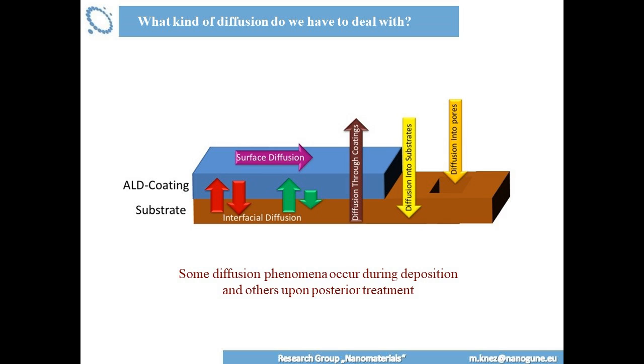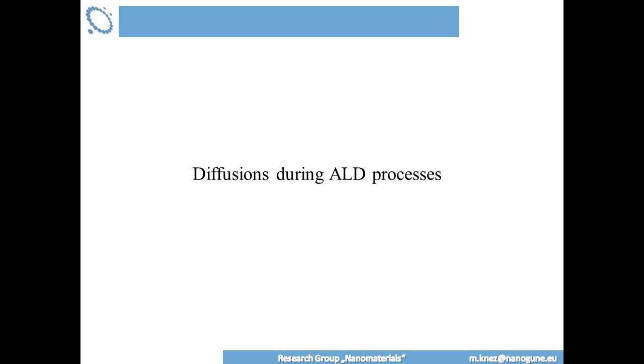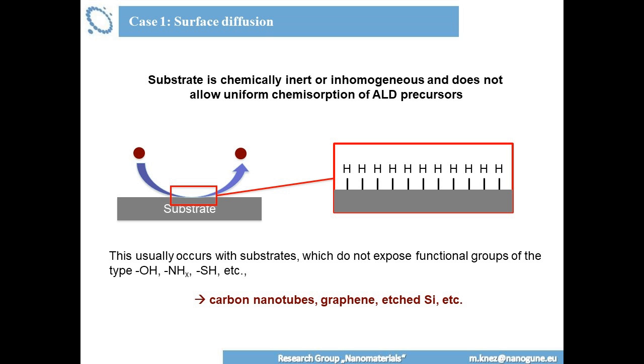But if you want to treat your sample after the coating, then you may have another set of diffusion processes. For example, diffusion of material at interfaces between two materials. So your coating and the substrate, for example, or a multi-layer coating. And you may have also something happening through the coating, either this way or this way. So these are the post-process diffusion phenomena which you need to take into account and to just think of in case that you want to have a functional material. Okay, let's go first of all into those diffusion phenomena which happen during ALD processes. So case one will be the surface diffusion.